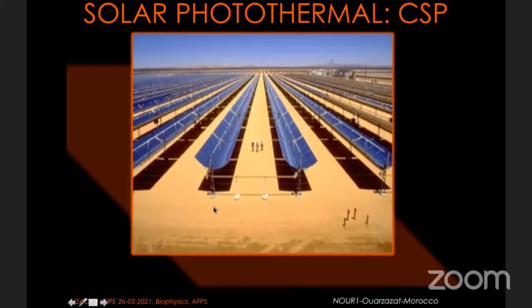And this is extremely important in CSP technology. This is the solar CSP plant at Noor 1 in Morocco. As you can see, you have here parabolic mirrors. And with these parabolic mirrors, you have a tube. And this tube here is a stainless steel or copper tube, and you have water. So light from the sun is reflected by this mirror to the receiver, to the tube here, to heat it. And by heating it, it will heat the water inside, and therefore that water goes through the standard cycle.